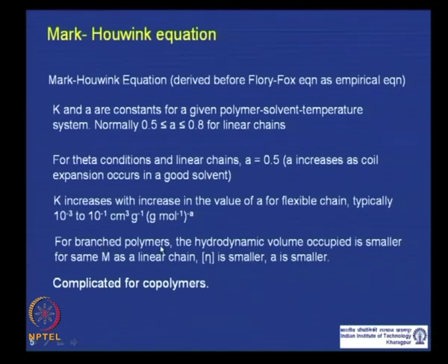Now, for a branched polymer, even if you consider theta condition, the expansion factor will be lower than 1 if you compare with a linear polymer. So, your a value could be lower than 0.5. For a linear polymer, a can never go below 0.5, but a branched polymer is more compact.